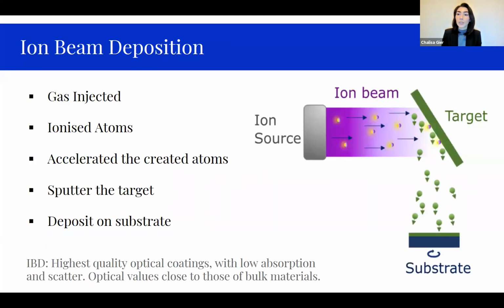And the technique that we use to fabricate our coating is ion beam deposition technique. How this technique works is that a gas is injected into the source, which is typically argon gas. The atoms are ionized and accelerated towards the target, sputters the target material and deposit this material onto the substrate. Ion beam deposition creates compact and durable films with properties closer to those of bulk materials, hence why this is the method of choice for high-performance optical coatings.